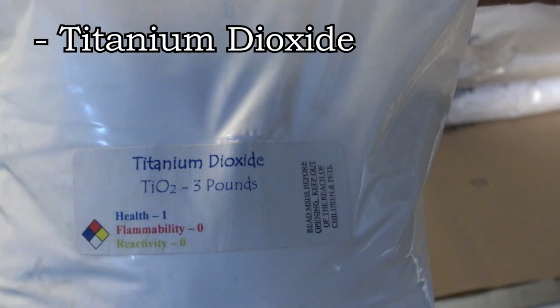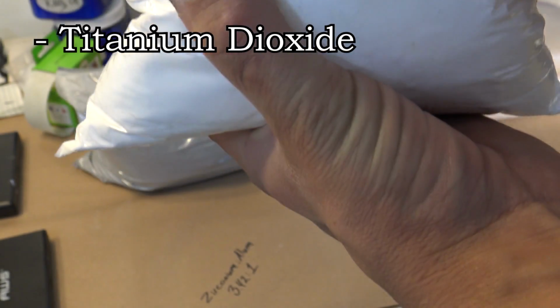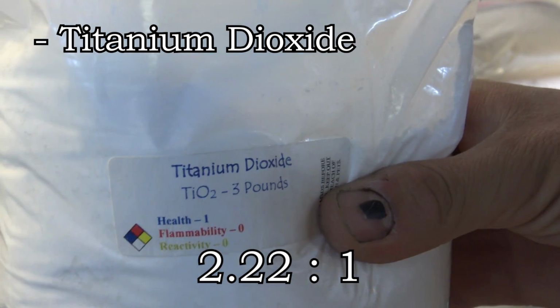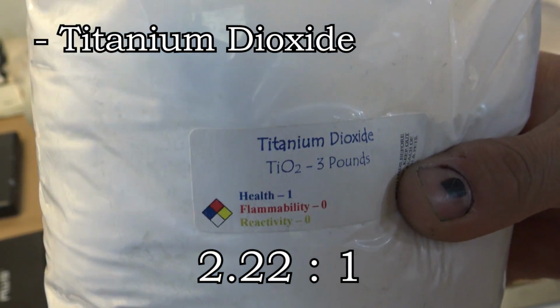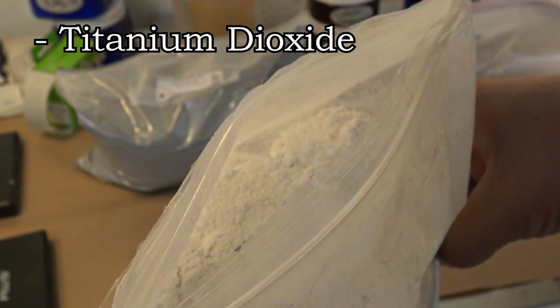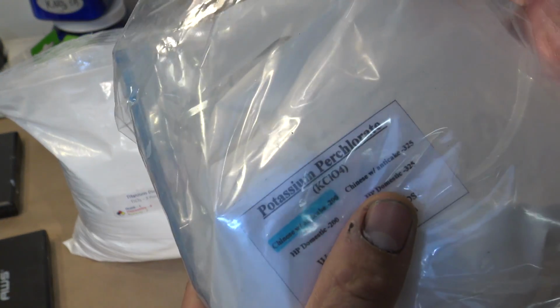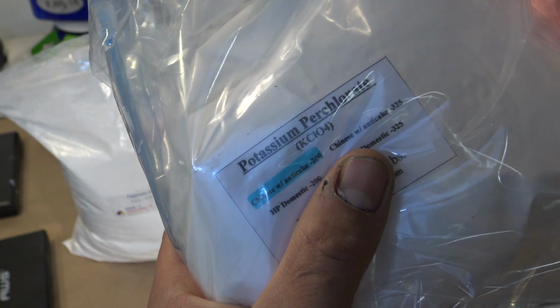The only problem is that it's a refractory oxide, meaning that the calculated 2.22 to 1 stoichiometric ratio isn't enough to reduce it to metal, instead ending up as a mixed reduced oxide. We're going to have to try something different this time, something much more dangerous than regular thermite. We're going to have to chemically add oxygen to the mix, which is about as safe as it sounds.